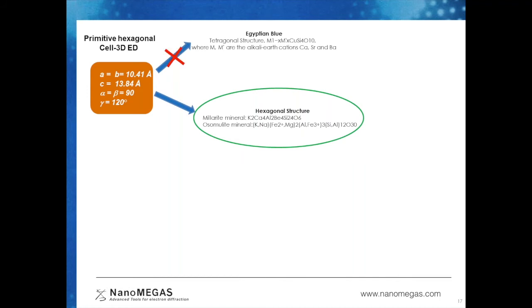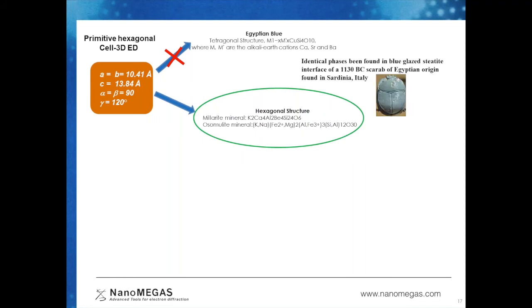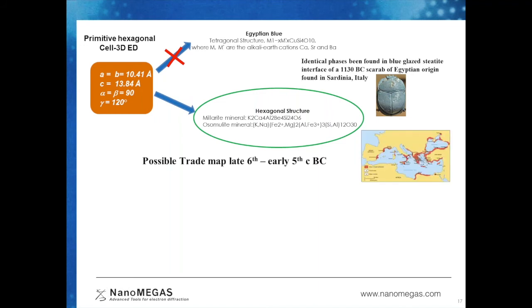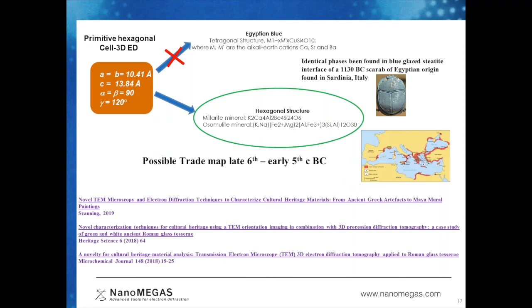And interestingly, the second one, which matches our results from 3D electron diffraction, is the same mineral also found in a 1130 BC scarab of Egyptian origin in Sardinia, Italy. As the same mineral was found in Greece, possibly there was a trade route between Egypt, Italy, and Greece in this period, and we also confirmed that from other literature sources. We have studied many other pigments from different glass amphoras, and all of the results we have published in three different journals.